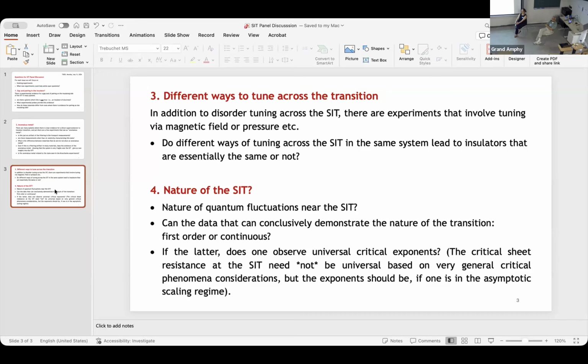But if the first order transition is correct, then the scalings must be wrong. Yes. There is no scaling. Absolutely, there should be no scaling. But in SIT, to get scaling, to have flat resistance as a function of temperature. In indium oxide, it goes up and down.